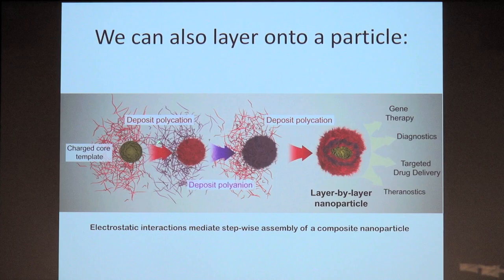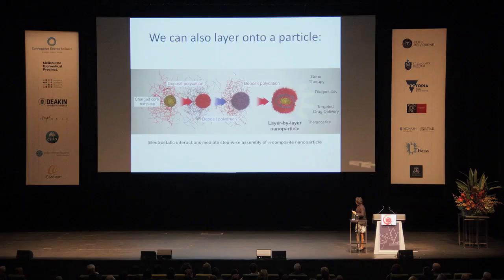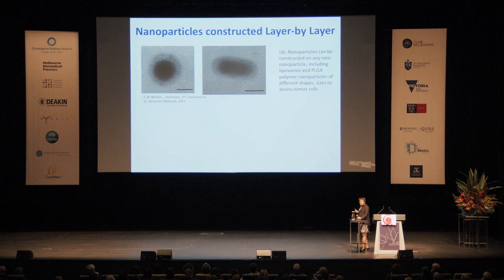And then we can rinse it, and then we can deposit another charged polymer. And we can continue to alternate to build up this film that essentially has layers of different types wrapped around the nanoparticle. It turns out that this is a very straightforward process, and we've been using this process to deliver therapeutics to very specific parts of the body.